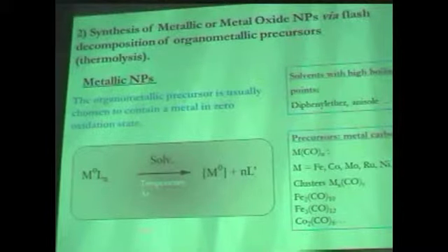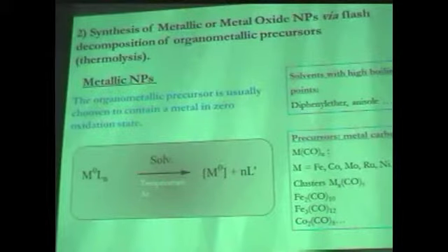usually in argon or nitrogen atmosphere, we decompose the ligand and we obtain the metals in zero oxidation state and the ligands which usually stay conserved on the surface of the nanoparticles. This reaction is usually performed at high temperature, around 250 or 300 degrees Celsius.